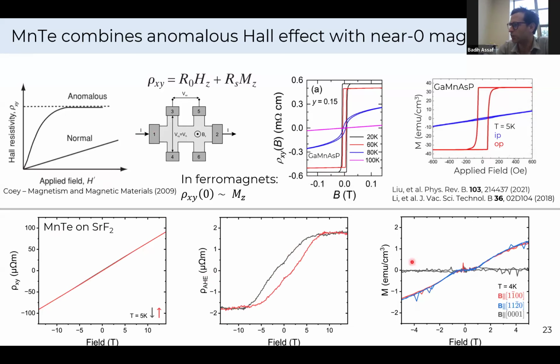So in the out-of-plane direction, the magnetization is nearly flat after we subtract the substrate diamagnetism, essentially. And then if I orient my field in plane along the easy axis, again, I see something flat at low field, and then at about 1 Tesla, 0.8 Tesla, the magnetization starts to ramp up. In antiferromagnets, that's what's referred to as the spin flop field right here. And this rise is linear and doesn't exhibit any hysteresis when you sweep back down.